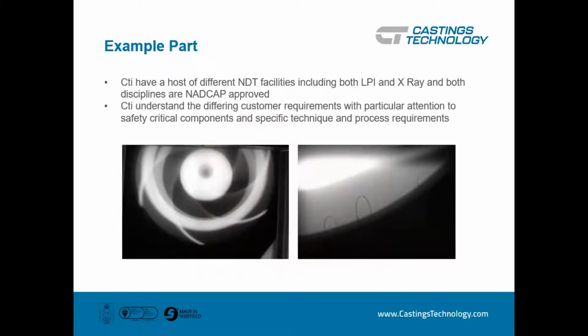And then, as most foundries have, we have a range of NDE equipment, including LPI, MPI, and X-ray. And again, you'll see that's a suction impeller there with some defects identified. Those defects might be in the form of an inclusion or a crack, and depending on the specification, that's assessed, and a repair is carried out, usually a grind out and a weld repair, and then it's retested to make sure that it meets specification.